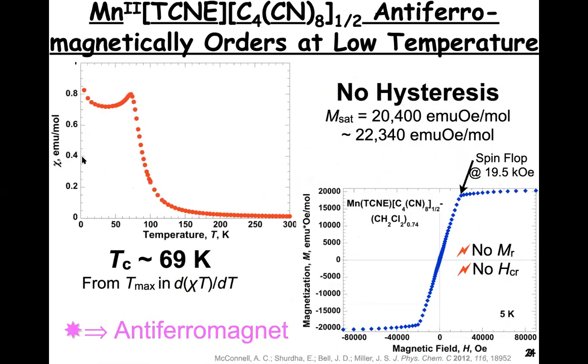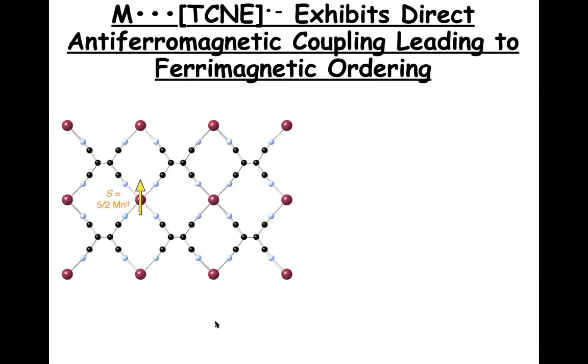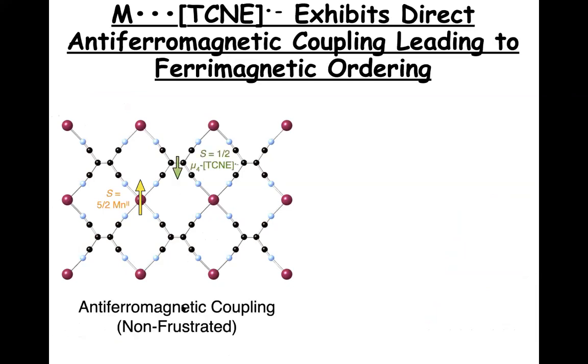If in fact we review the susceptibility versus temperature, we see a cusp in the data. If we look at the magnetization, we do not see any hysteresis. And in fact, this material is a bulk antiferromagnet, not a ferrimagnet, a bulk antiferromagnet. Now, I'm sure everybody's familiar with antiferromagnets. You have spin up and you have spin down, they couple. And the way you make this magnet is you look at the manganese has 5/2 spin up, it antiferromagnetically couples to the TCNE radical anion, which is 1/2 spin down.